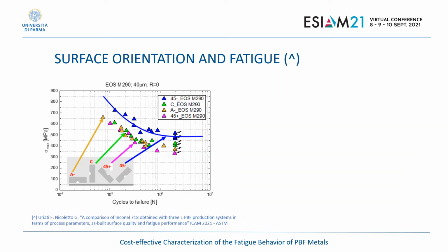The specimens with the different surface orientations have been tested in fatigue, and here in this plot we see the results. We can see that there are differences among the different orientations. Especially, there are three orientations that lead to similar trends, but there is one specific orientation, the 45 minus orientation, that is characterized by a clearly better fatigue response. This diagram is part of a larger presentation that we are going to give in a future conference, ICAM 2021, for the interested people.